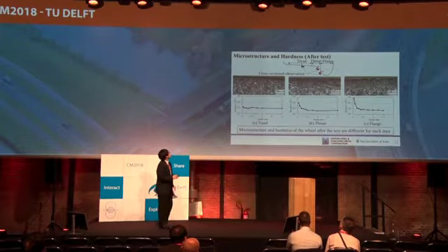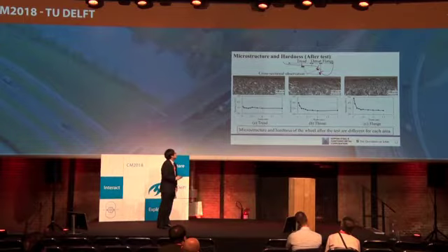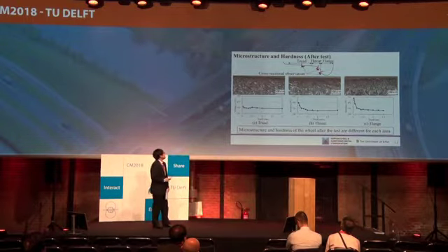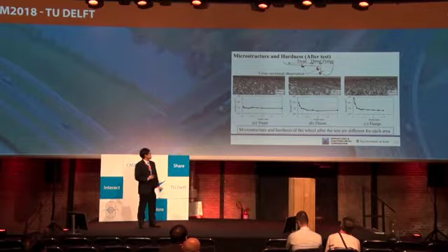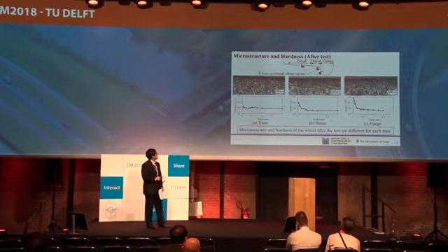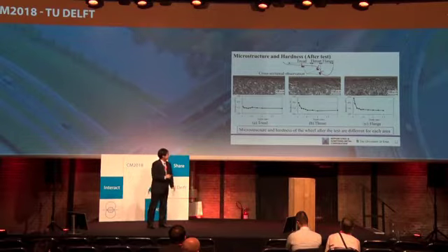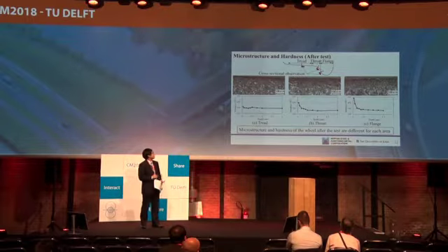And lastly, this figure shows the microstructure and hardness after the test for tread, throat, and flange. The microstructure and hardness of the wheel after the test differ for each area, because the throat and flange areas receive high force.